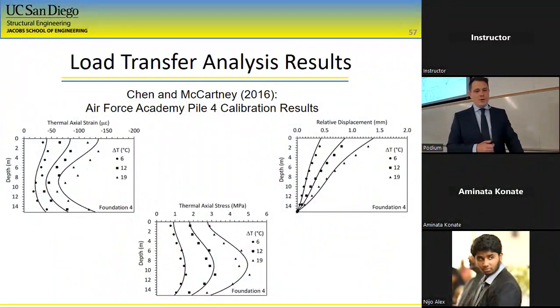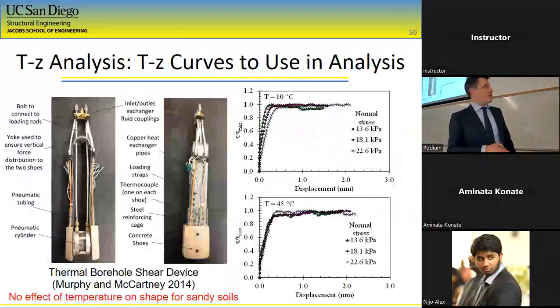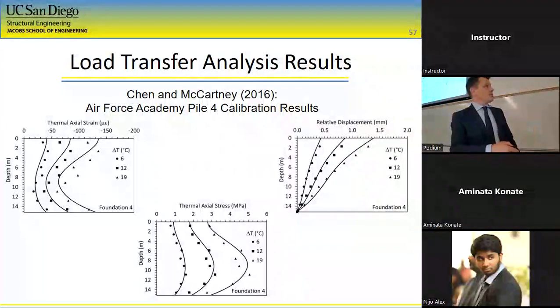Then we put that into our load transfer analysis and compared our simulations or our calculations with our measurements. And in general, we got pretty good representations of the thermal axial stress with depth. So this is why it's a very simple tool. All we need is this curve and then an estimate of the ultimate capacity with depth, and we can predict the thermal axial stress profiles.